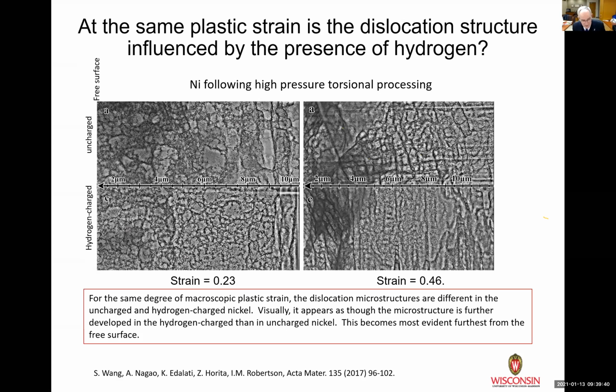So again, this is work done by I²CNER, looking at nickel following high pressure torsional processing. The upper images show the uncharged material, and the lower one shows the hydrogen charged material at two different plastic strains. Now, the beauty of the torsional processing was that the materials were getting the same plastic strain. And by picking the same locations on the samples, we could say that those samples had experienced the same plastic strain. If you look at the upper image on the left, you'll see a dislocation structure, but you'll also notice that there's areas where the dislocation structure is poorly formed, and some of the cells are actually really quite large.